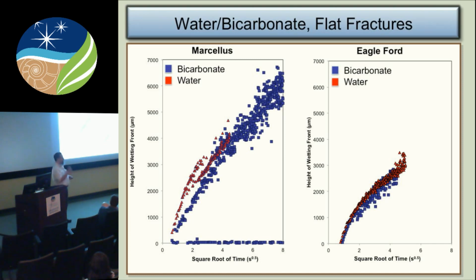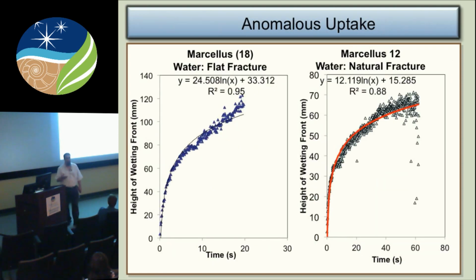However, changing the fluid composition, in this case we didn't have these at temperature, so our approximation of CO2 was to saturate the rock with the fluid with bicarbonate, and you can see it made very little difference to the rates here. There's a big difference between the Marcellus and the Eagle Ford, but essentially no difference that we can measure between pure water and bicarbonate saturated water. I've got data for sodium chloride saturated water and for slick water as well that there's no time to show here. However, this is one thing that is important.